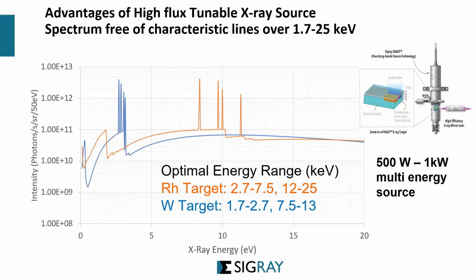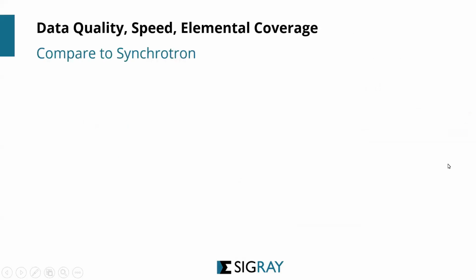the much lower intensity part of the X-ray spectrum, in order to get the range that we need, notably during XAFS type of collection. So for instance, we can switch from one energy to another energy so that you can have a spectrum that is free from the characteristic lines, whether you are working with elements from 1.7 keV or 25 keV. And that is a high power X-ray tube with 500 watts and with multiple energy sources.